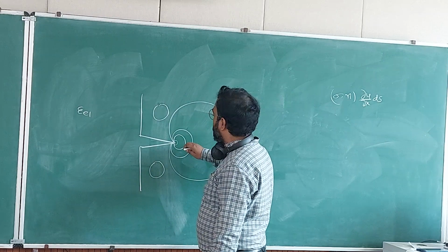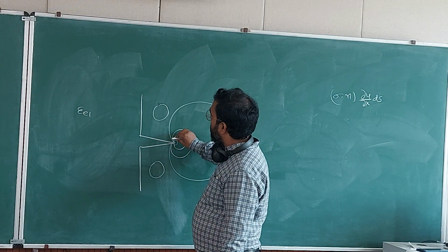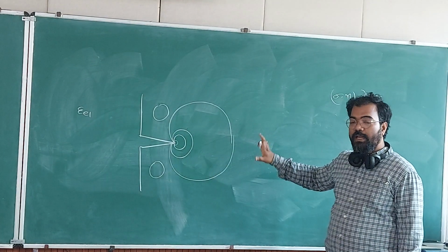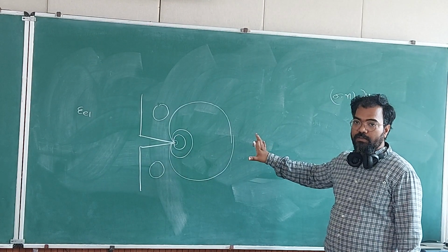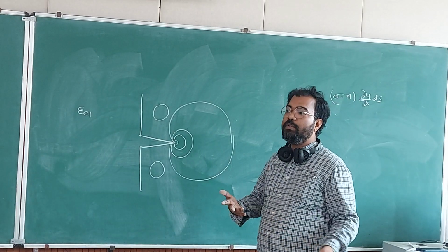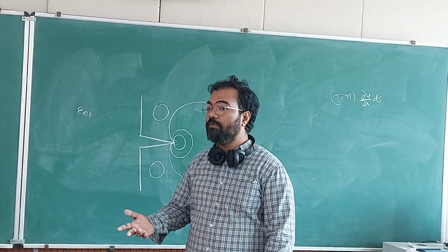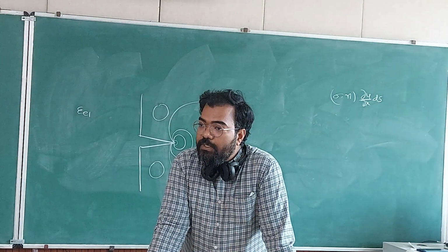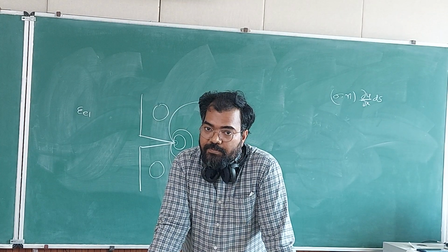So at one point the creep zone will engulf the whole sample, and everything will be deforming plastically because you don't have to increase the load. Basically what is happening is that the material is getting viscous with time. The material is becoming softer. Steel is becoming chocolate. That is what is happening.